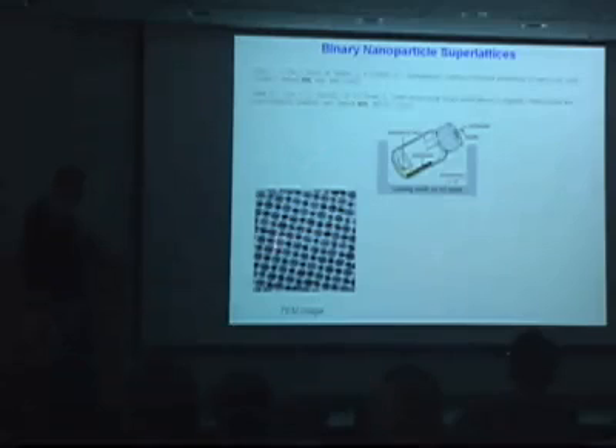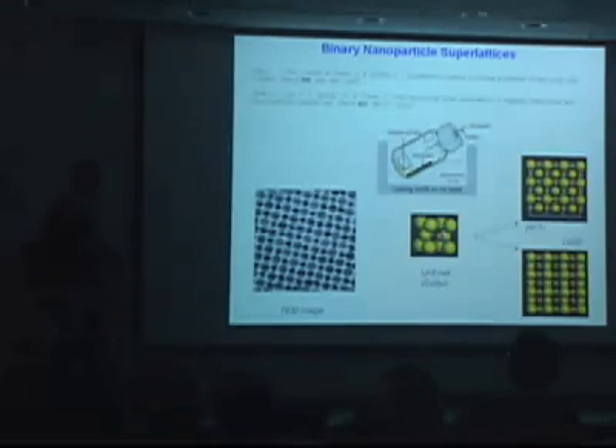and the particles will pack themselves into pretty sophisticated two-dimensional and three-dimensional binary arrays. Like, for example, in this structure that was self-assembled out of solution, the gray spots correspond to lead selenide nanocrystals, and the dark spots are gold nanoparticles. We usually study these structures by transmission electron microscopy in real space. That's a big advantage of these materials, because you can study crystal structures with single particle precision in real space very easily.